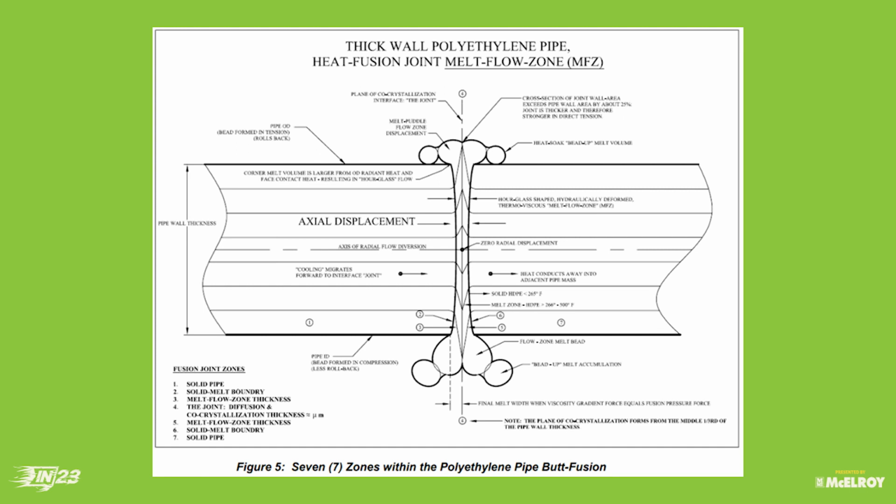And also, something that we haven't touched here is that large pipe diameter also means differences in temperature between the top and the bottom when you are outside, and also related to the heater. Sure. So if you add those variables, then you have problems. That's why you need to capture the 5 variables that ASME Section 9 asks you for: qualification of the operator, the fusion machine, pipe, temperature condition, and weather condition. So this is something that I highly recommend. Yeah, absolutely.